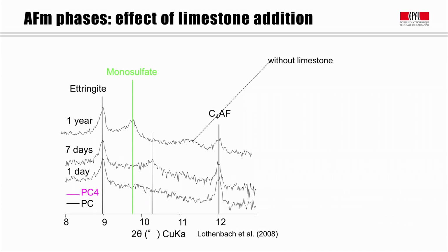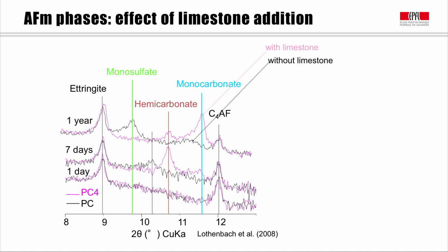3 or 4% is typical, because this amount of limestone has been shown to improve properties and at the same time gives us a slight reduction in the net CO2 emissions. And when we have those cements with limestone, then we can see the picture changes quite dramatically.